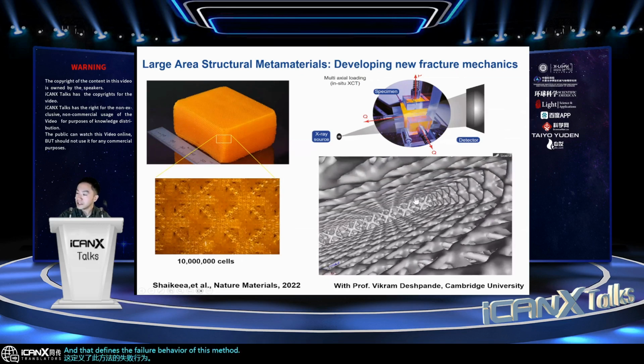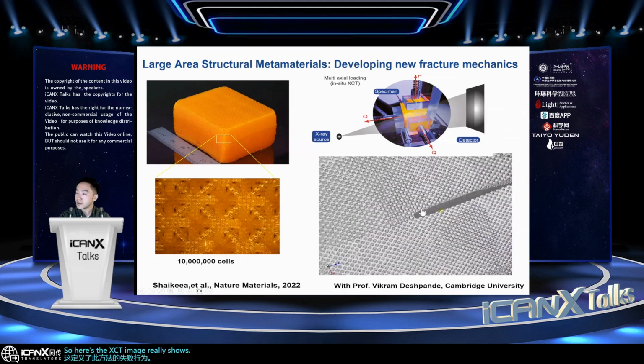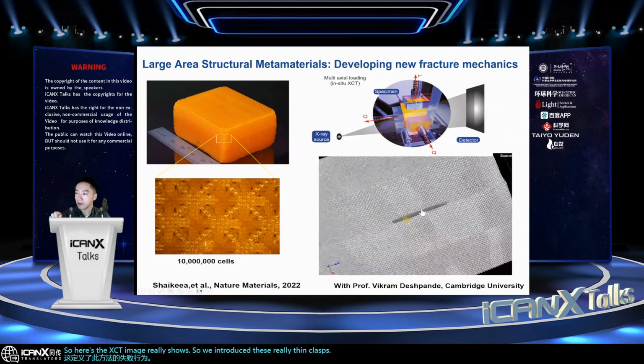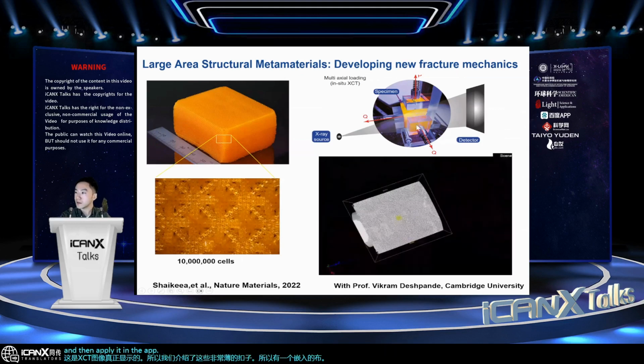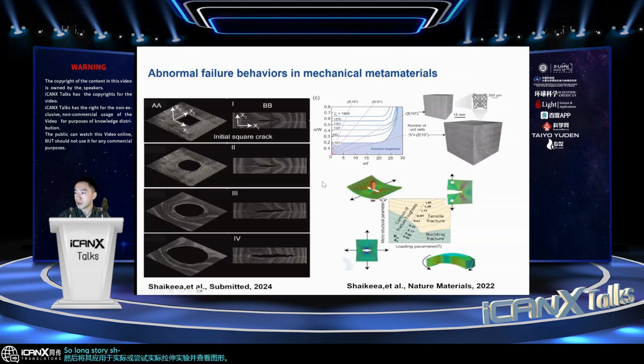Here the XCT image shows the really thin cracks that we introduced. This is an embedded flaw, and then we apply uniaxial or triaxial tensile experiments and look at the failure mode. Long story short, we really observe very different and exotic mechanical behavior that you don't see in continuum materials. One example: we intentionally made the raw material, the base polymer, an elastic brittle material. An elastic brittle material is one that, when you have a crack and load it, will fail catastrophically. But what we really observed lately is that they don't fail catastrophically.